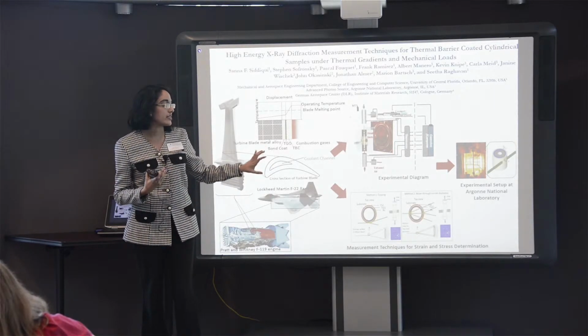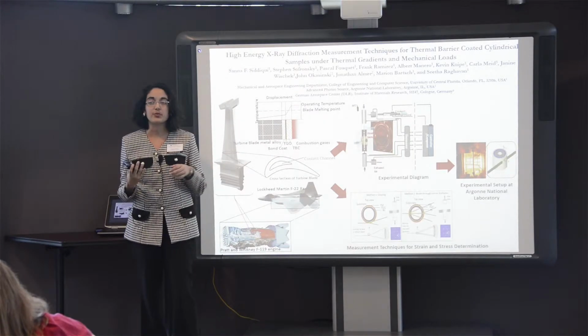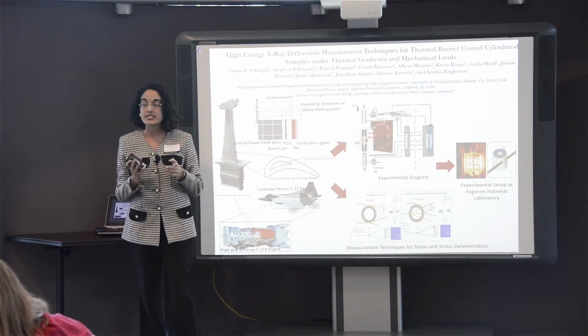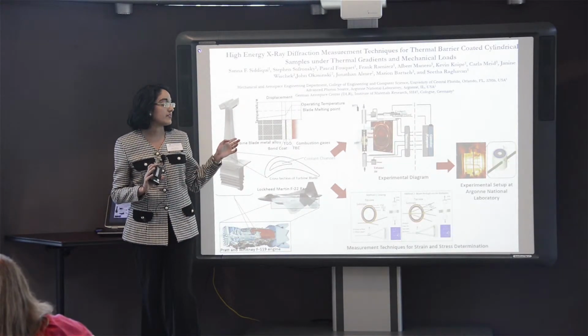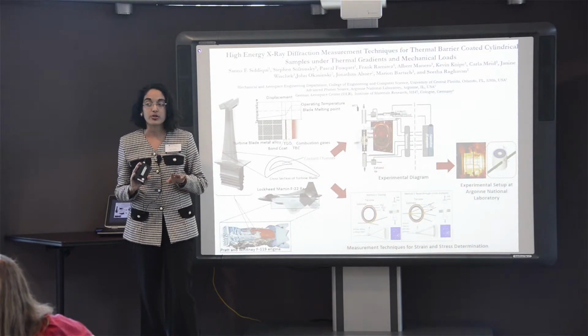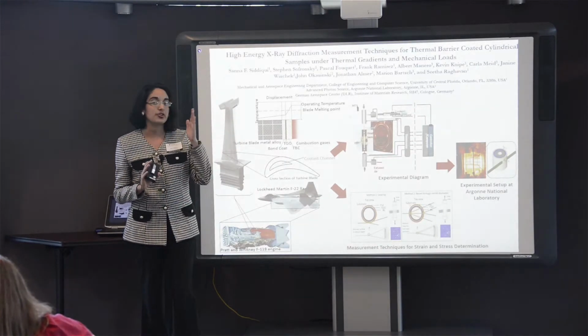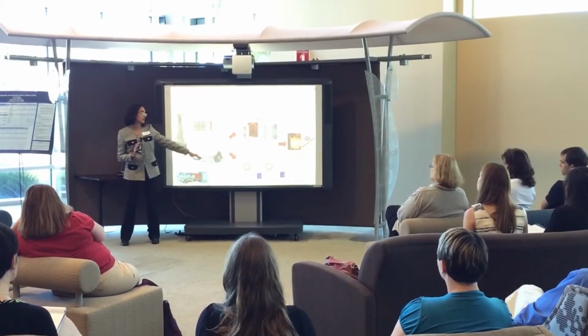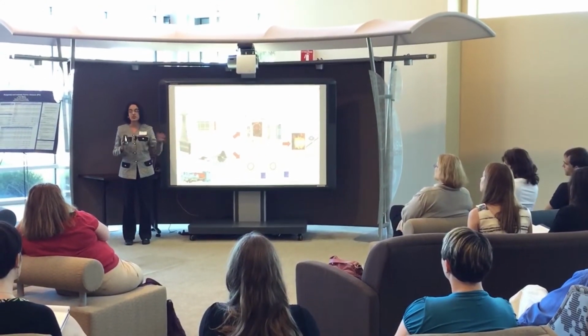And another part of this study that's very significant is we've been able to apply uniform heating on the sample to ultimately achieve a uniform thermal gradient across the sample with internal cooling, and that is very similar to an actual realistic turbine blade where you have coolant channels for cooling of the internal substrate.